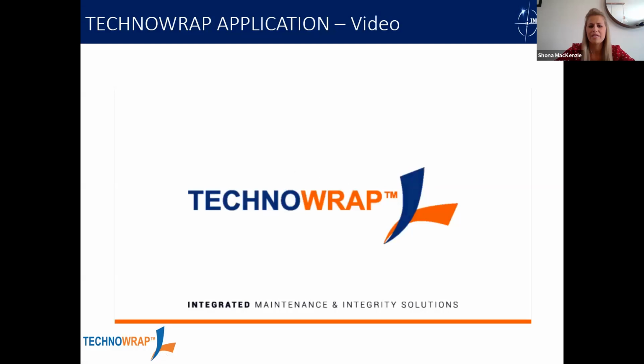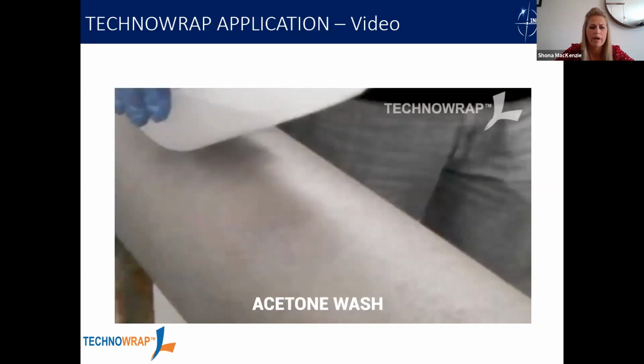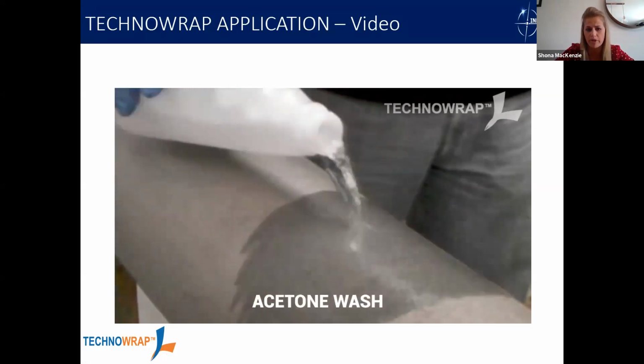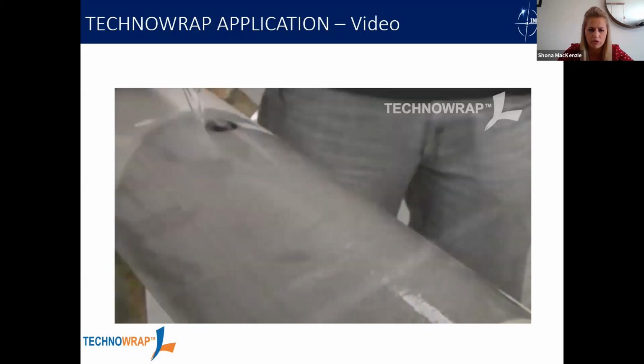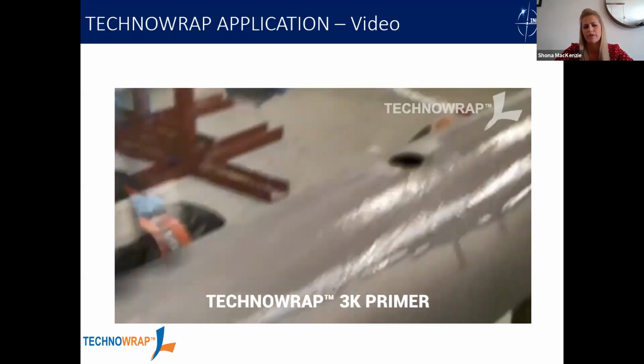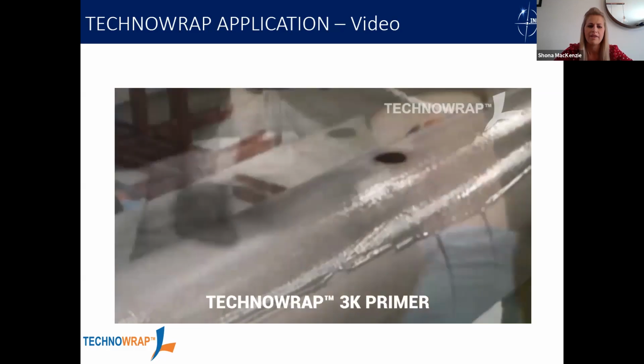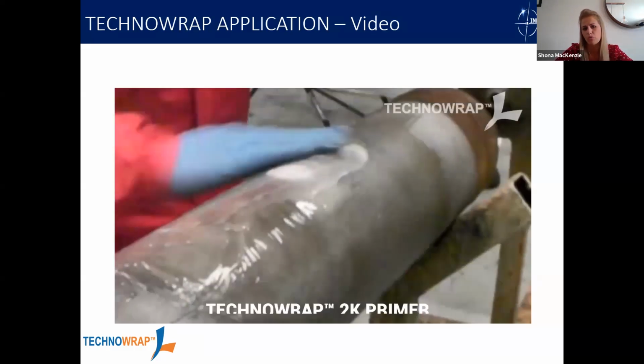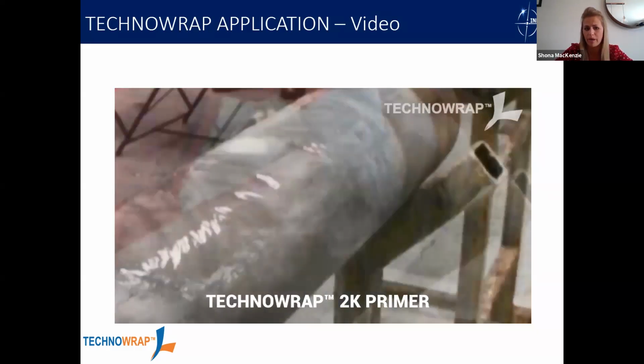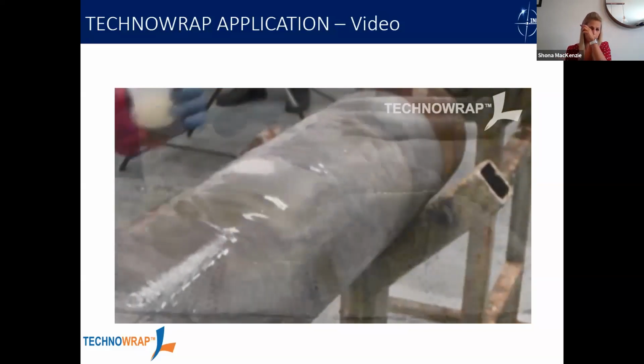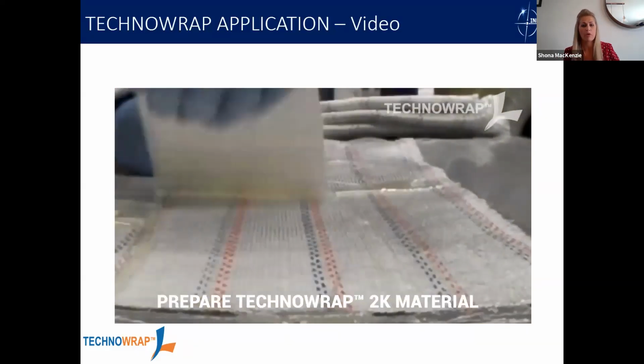Okay, so a basic installation of composite repairs requires a surface preparation element at the start, so that's not included in this video. So we've assumed that this pipe's been blasted, and what we do is we use the acetone wash to clean off any debris on the pipework, and then we prime it using an adhesive primer.